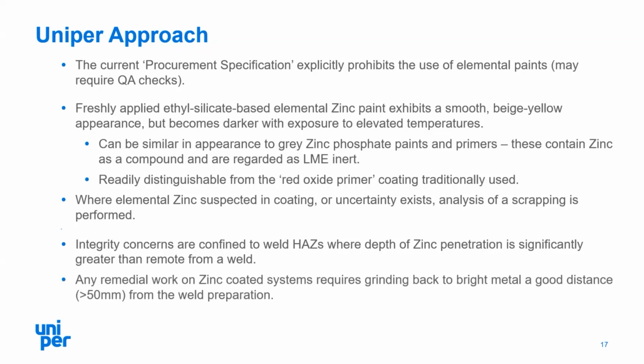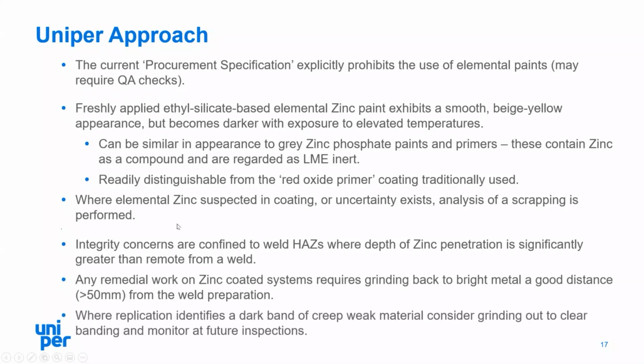Furthermore, for any remedial work on zinc coated systems, the surface should be ground back to bright metal for up to 50 millimeters away from the weld preparation, so a couple of inches away, to really ensure that there's no risk of getting zinc infusion or liquid metal embrittlement or anything taking place. And where replication identified a dark band of what we would now consider to be creep weak material, then the grinding out to clear out that banding would be prudent, and also to monitor the condition of the components at this position at any future overhauls.